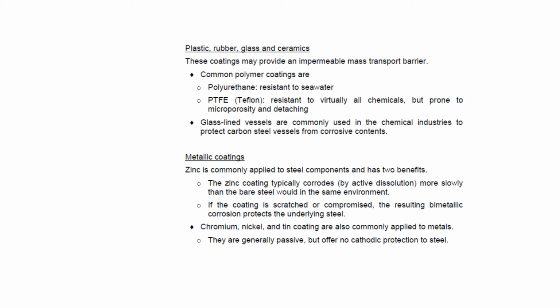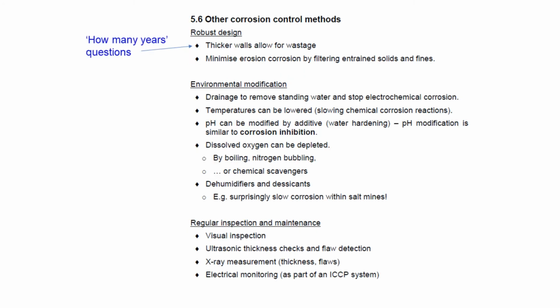And another thing to say about zinc is that its kinetics for dissolution are quite slow. So even though you think it's a reactive metal and it's going to be lost quickly, its exchange current densities are low enough that it's lost fairly slowly, and it's a good coating. Other kinds of metal coatings, chrome, nickel, tin, these are very commonly used as well. These things are often passive, but they don't offer cathodic protection to the steel, because all of those things are, well, they're not substantially more reactive than the steel. In the case of chromium, they're not more reactive because they become passive.